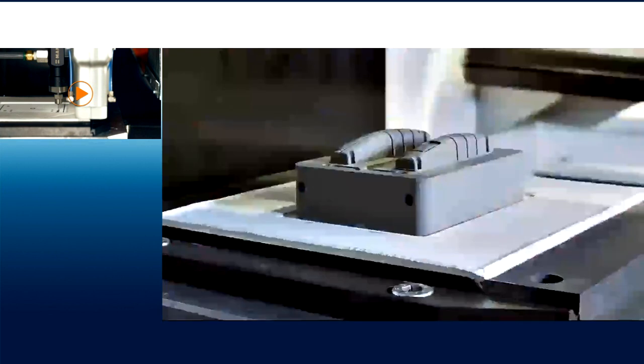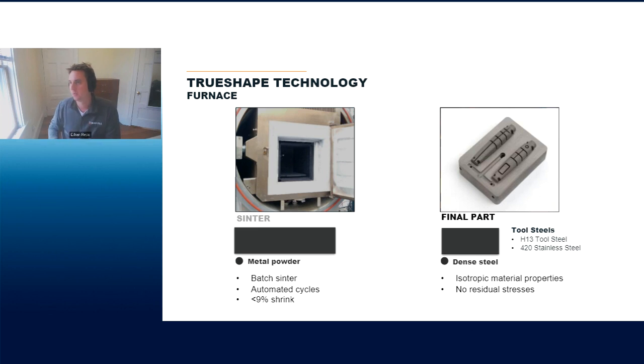Let's finish here. Awesome. So once printing is complete, then we go into a furnace. What's happening in the furnace is a sintering process. This is very similar to what happens in a metal injection molding process or binder jetting process, where the part actually shrinks inside of this furnace. The metal powder actually fuses together, the part densifies and comes out as a dense, strong metal part. So the part does shrink about 9% in this process in the furnace. Our software, of course, accounts for that.